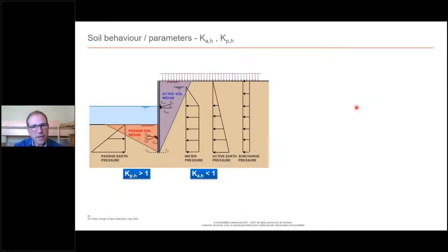Now, once you have this Ka and Kp, you can determine the vertical pressure at a certain point of the soil. You can determine the horizontal pressure due to the soil, due to the water, due to the surcharge loads on the active and on the passive side. And you can also take into account the cohesion. There are different formulas, so I won't go into the details, but this is the one that we use normally in Germany, where you reduce the active pressure when you have a cohesion, and where you increase the passive pressure if you have a cohesion, you multiply the square root of the K with 2 and you add it.